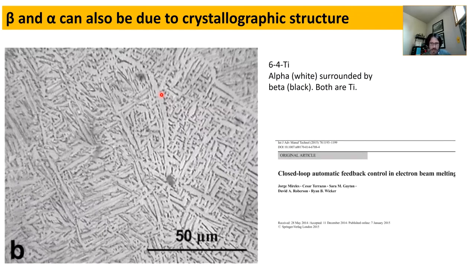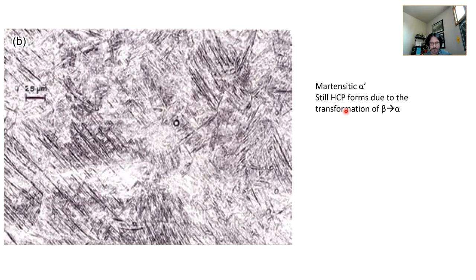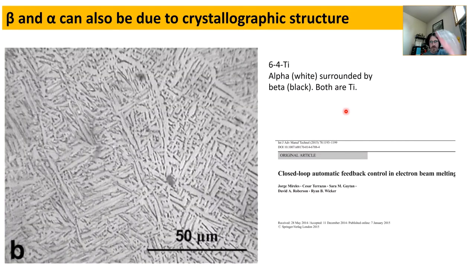This is the paper it came from — we put it out, submitted in 2014. A little older work. The alpha is surrounded by black, and the beta phase kind of segregates to the grain boundaries of the alpha. This is also showing martensitic alpha prime — you can see the difference in morphology with the hand here, comparing this alpha-beta microstructure versus the alpha prime. It's still a dark phase.